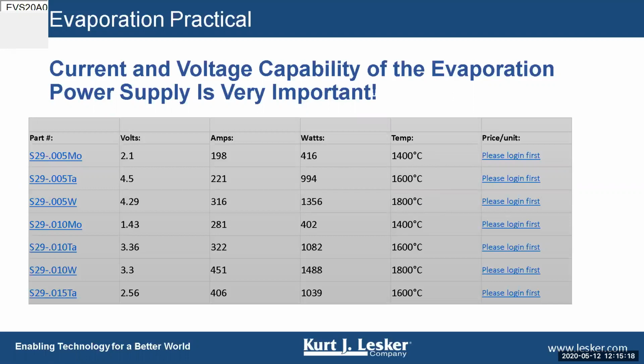What happens if your power supply only gives off 2 volts max and it's limited to 200 amps? Well, if it's limited to 200 amps, certain of these sources require more than 200 amps to reach a critical temperature. So it's important to consider the output of your evaporation power supply.